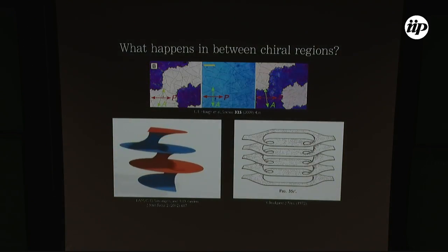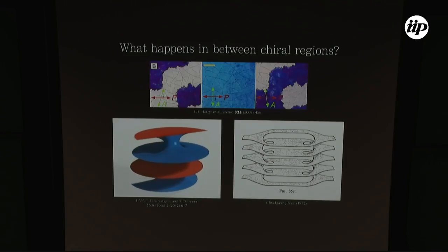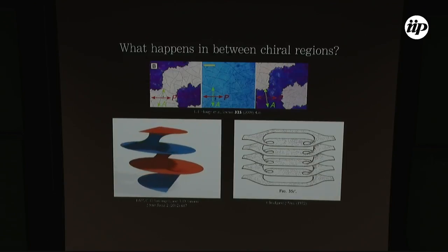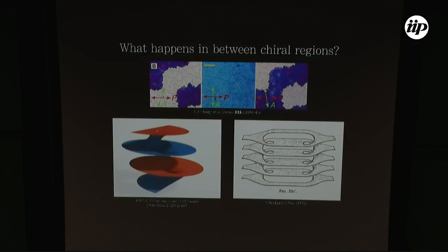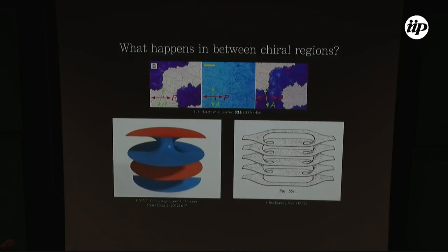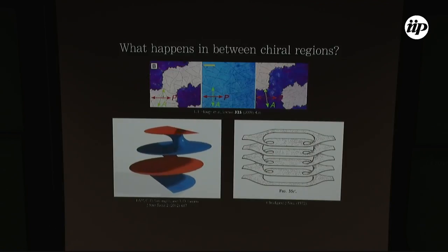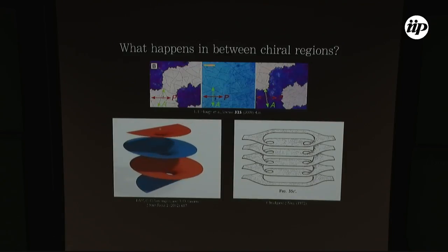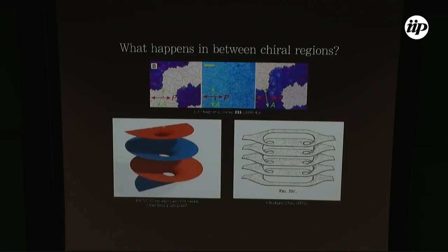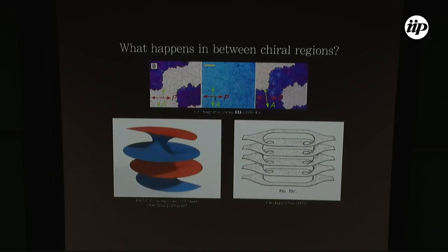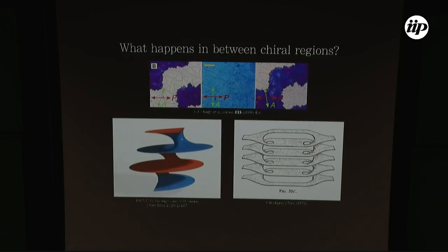And I guess this is the last thing. This is an open question. This is another image from the original paper on the helical nanofilament phase. And what this is showing is that you have these huge regions of homochirality. I didn't mention that the width of each of those bundles is about 20 nanometers, the half pitch length is about 100 nanometers, and this scale bar is, I think, 100 microns. So you have these massive homochiral regions coming from these very, very tiny chiral constituents.